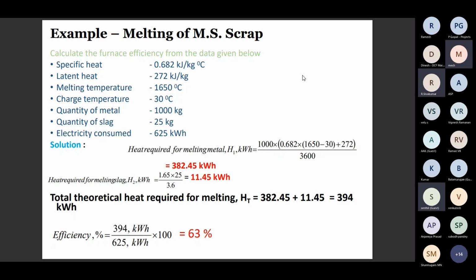The electricity consumed by the furnace is 625 units. So first we have to calculate the theoretical value. Substituting these values in the above formula, we get around 382.45 units only required for melting this particular material from 30 degrees to 1650 degrees. And for the slag it needs another 11.45 units. So totally the heat requirement is somewhere around 394 units, required for heating the metal from 30 degrees to 1650 degrees for melting 1 ton of metal.